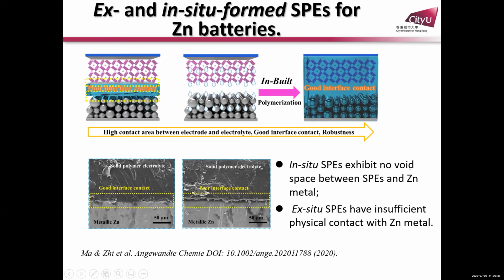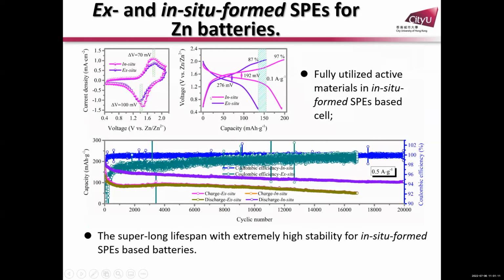The solid state batteries, the idea is from lithium batteries. In the beginning, I was trying to use ceramics, but until now, I didn't find any ceramic-based electrolyte that can be useful for zinc, because zinc is difficult to diffuse. But with polymer, if we in situ polymerize some polymer with low molecular weight, we can have a very good interface. This is the non-in situ polymerized one. This is how we optimize.